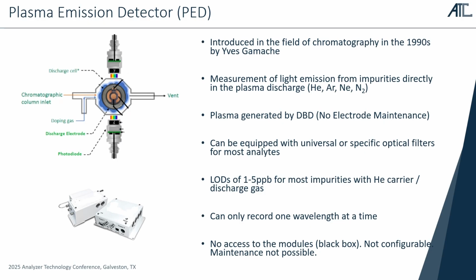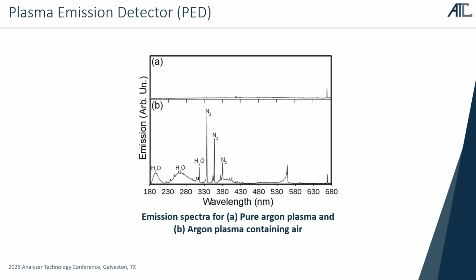And since it is not using this photoionization mechanism that relies on helium, you can use other carrier gases like argon, nitrogen, and neon. But still, this technology from the 1990s suffers from some drawbacks. For example, you can only record one wavelength at a time, and also you have no access to the optical module, so it's kind of a black box that is not configurable, and maintenance of the optical components is not possible. Here you have an example of, at the top, a clean argon plasma, and then at the bottom, light emission from nitrogen in the argon plasma. So you can see that if you want to measure nitrogen, you can select some wavelengths that are specific to nitrogen and be really sensitive to this compound.